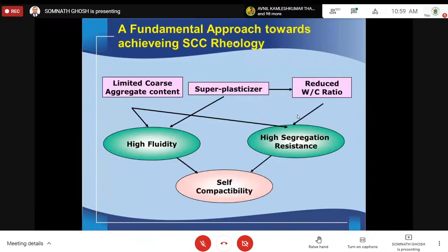Now you see, just try to understand the fundamental approach towards achieving self-compacting rheology. You are limiting the coarse aggregate content, so it is related to segregation resistance. Superplasticizer you are using, it is giving you fluidity. Again, it has got relation with segregation and relation to fluidity. If the material is segregated, you can't use it. Then if you go for very high water cement ratio, then you can't really produce cohesive concrete. It will be segregated. Naturally, if you take all these things together, they are interacting with each other, then only you can achieve self-compactibility.